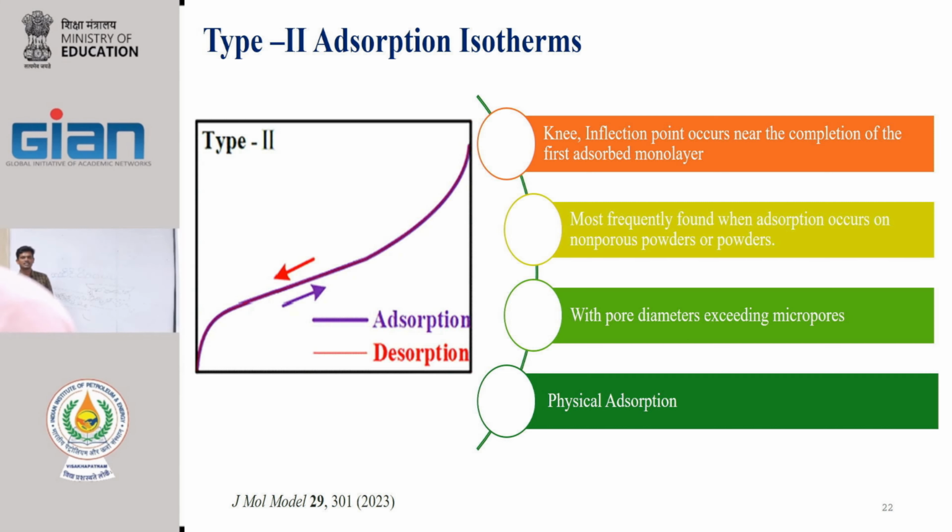I agree. Especially in MOFs, whenever you see these things, experimentally you also see the condensation. Condensation does happen. I mean, you see the hysteresis loop in MOFs, but it is too narrow. Yeah, too narrow, because we are not going that far. In MOFs, usually the pores are of, I don't know, even 2 nanometers is big. Usually we have only 1 nanometer. That's true.